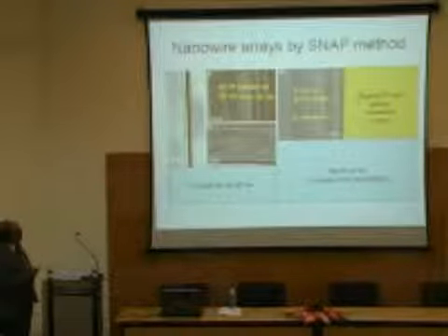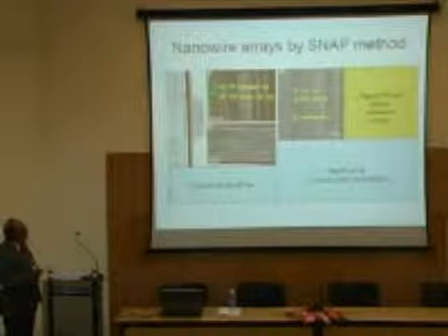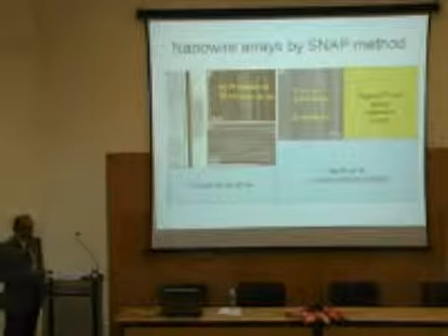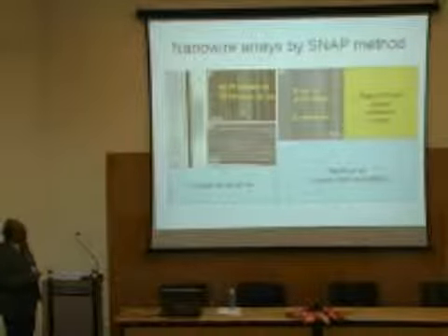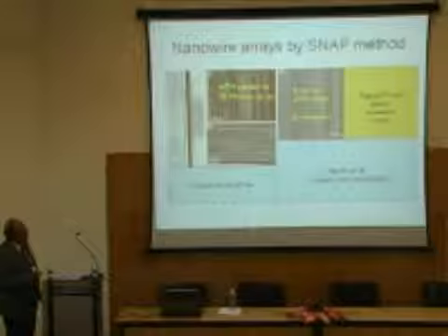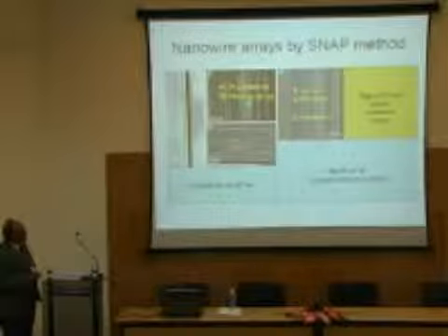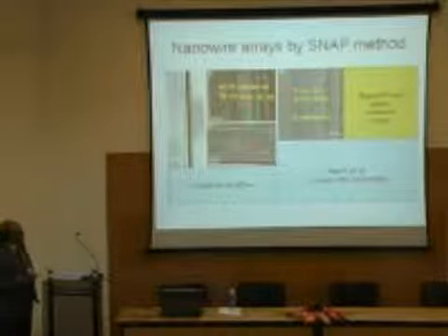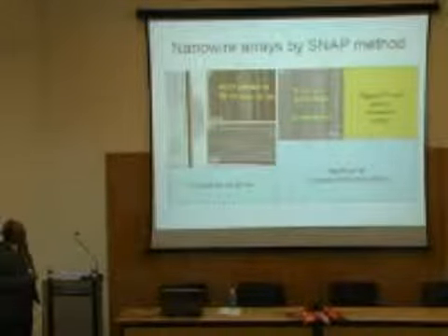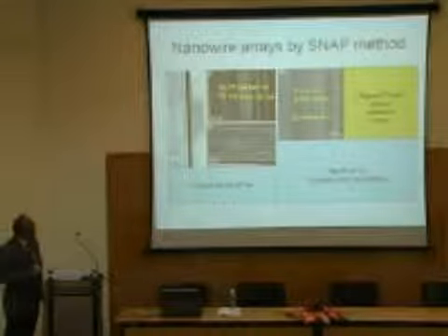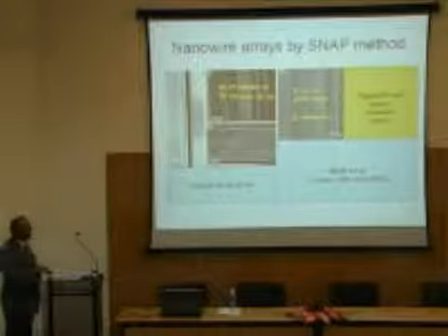So this small area is like 0.1 microns, and if you blow this up, you will have a very regular array of nanowires, and the challenge is to reduce this distance between the wires. So you have to reduce the diameter of the wires, and also you want to reduce the distance between the wires, which is called the pitch. And you can see here it is around 60 nanometers, and you can generate 16 nanometer in silicon. So a lot of work has been done by James Heath at Caltech on aligned platinum silicon nanowire assemblies.